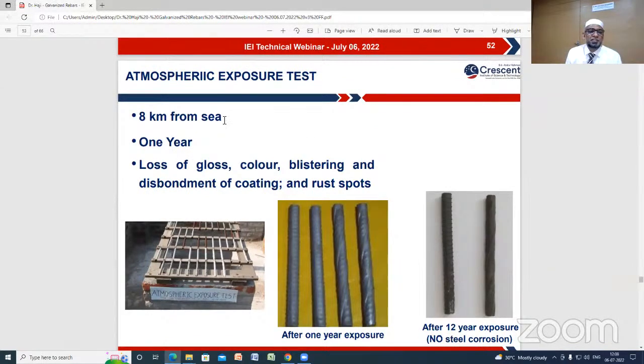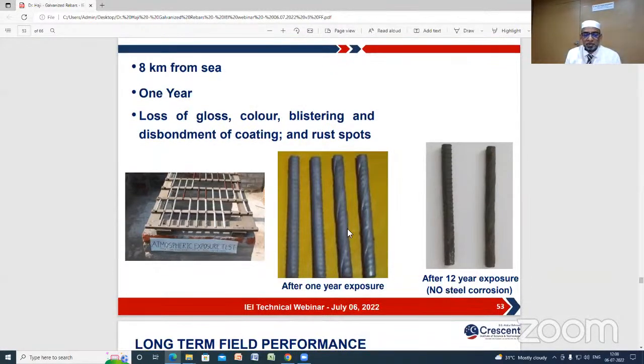For curiosity's sake, we did some atmospheric exposure tests. Galvanized rebars were placed in a residential area 8 kilometers from the sea and monitored for even 12 years. This is the picture of the galvanized rebar after 1 year of exposure outside. There is no visible corrosion of steel, only minimal corrosion of zinc was observed. This is the same specimen after 12 years of exposure. Even now we can see no visible signs of corrosion of steel. So it clearly indicates that its atmospheric resistance is very, very good, even for site conditions where it is kept for a few months. So no need to worry, you can use this.